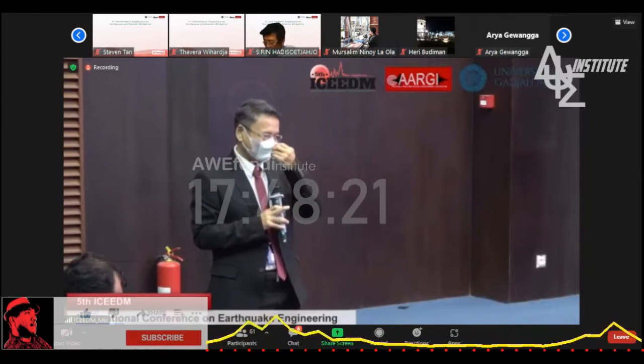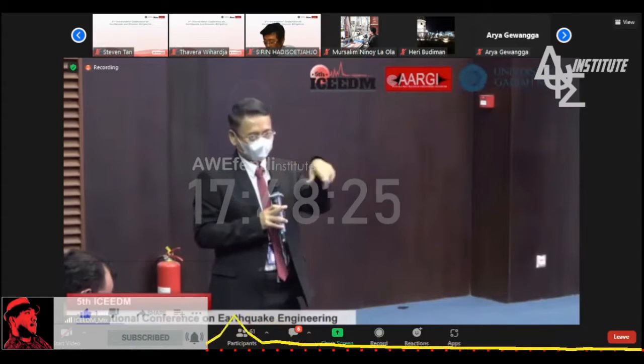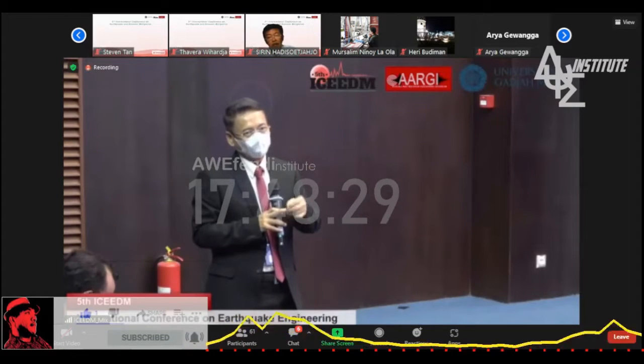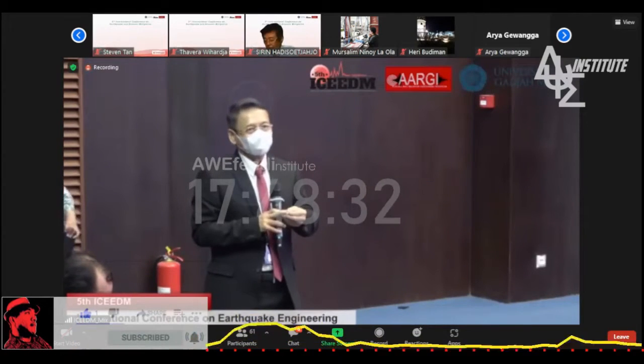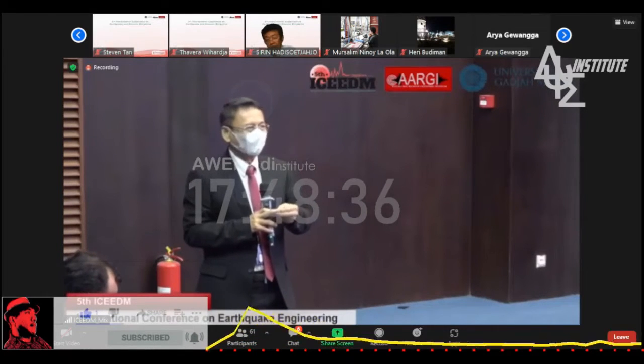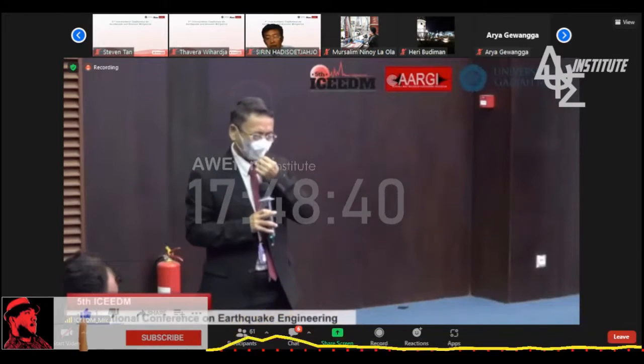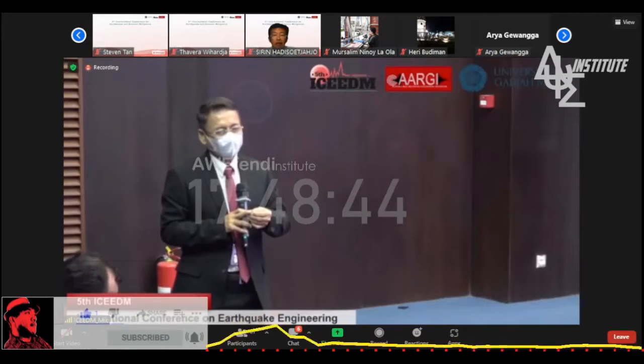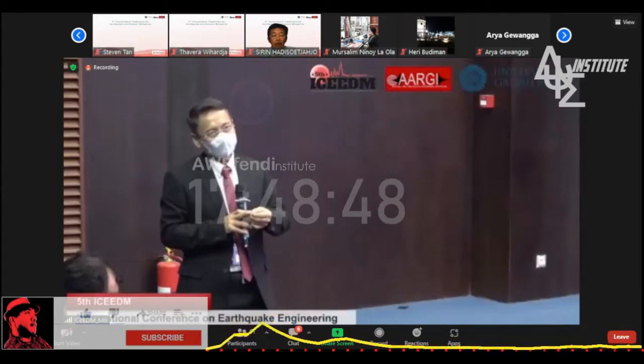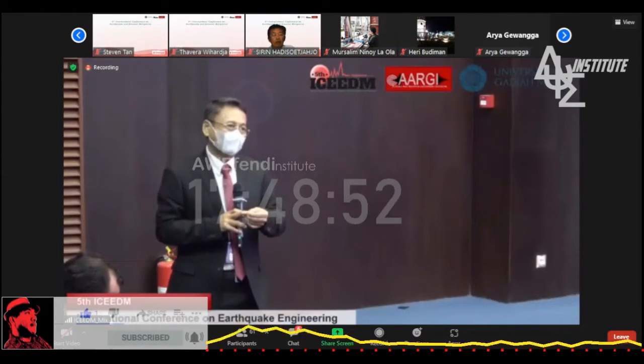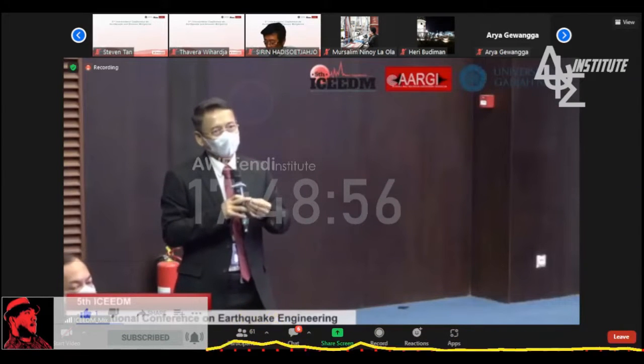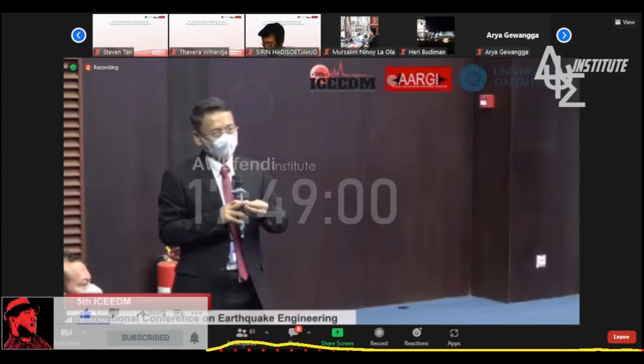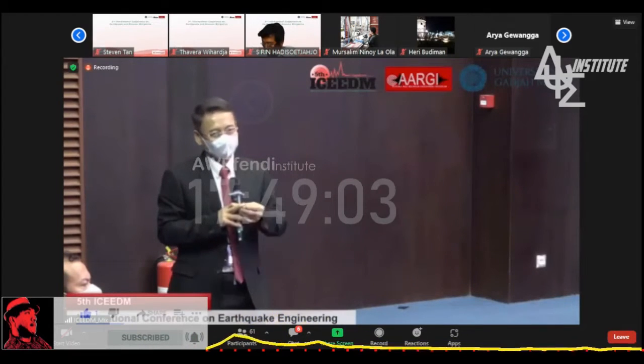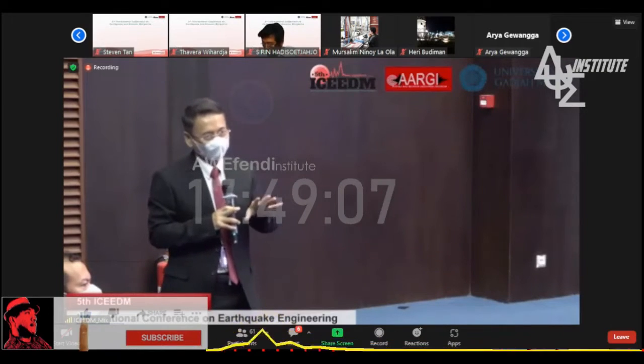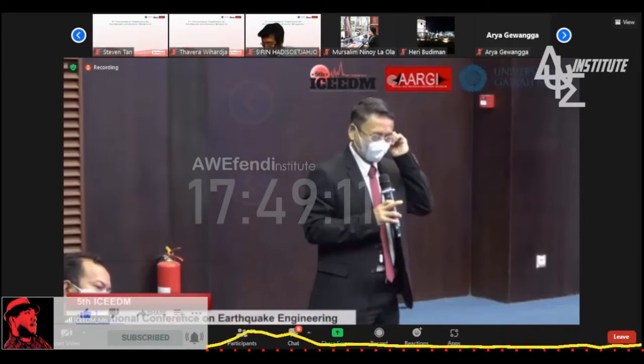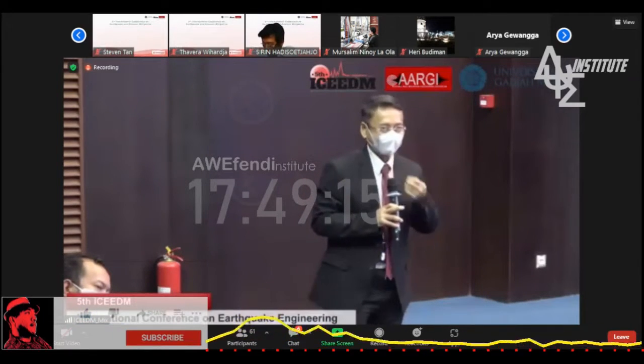The second thing is relative to the shrinkage of the inner concrete. In the long run, maybe the interface between the inner and the outer will be disturbed in the interface zone. That's why the requirement says that in terms of modulus of elasticity, the difference is less than 15%. However, if you use the strength, it's around 50% different. If we take the regular formula, E is equal to 4700 square root of fc prime, it is close to the requirement that we have: 15% for the modulus and 50% for the strength. Okay, thank you.